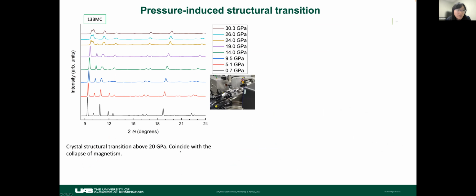Okay, and then we asked ourselves what happened to the crystal structure, and what is causing this suppression of magnetism, and whether this Kagome lattice motif is disrupted under pressure, which could be causing the suppression of magnetism, because the magnetic state is likely very heavily impacted by the flat band in the band structure mentioned earlier. So we did several rounds of X-ray diffraction experiments at 13-BMC, and we found above 23 GPa, pretty consistent with the suppression of magnetism at room temperature, there are some peak splittings, and there is definitely a crystal structure transition going on that coincides with the collapse of magnetism.